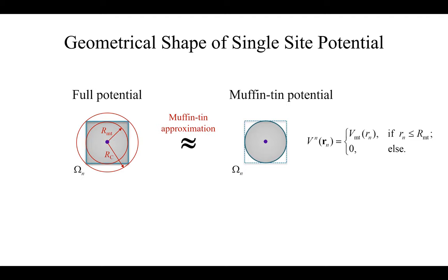So this kind of approximation becomes bad. But part of it also has to do with crystal symmetry. In a typical semiconductor like germanium or silicon, you have a diamond lattice, which has a lower symmetry. If you have a typical FCC or BCC, a higher symmetry cubic material, a sphere is a much better approximation. The lower the symmetry, the more you expect that the spherical approximation is probably not as good. Right. What do you mean by symmetry there? The diamond has only four neighbors and the other ones have more neighbors, and that makes it more spherical, right?